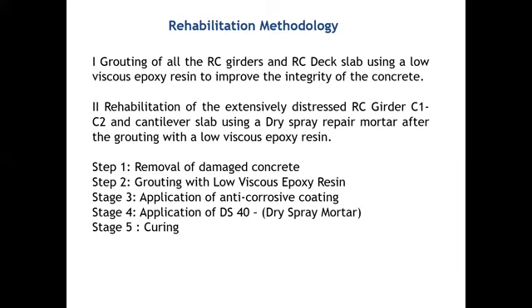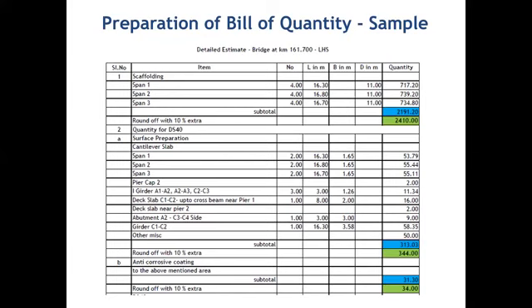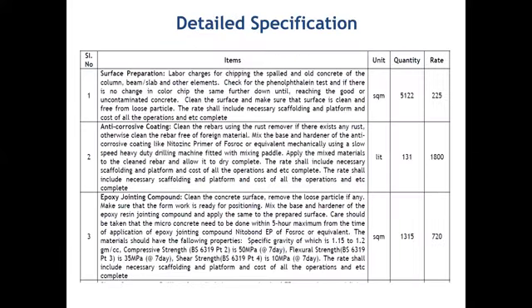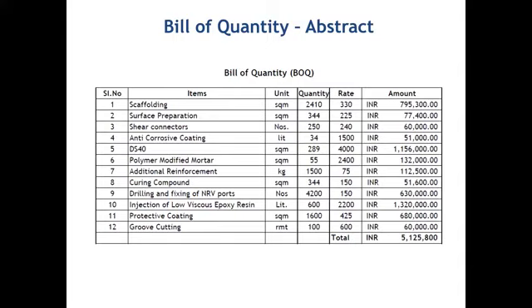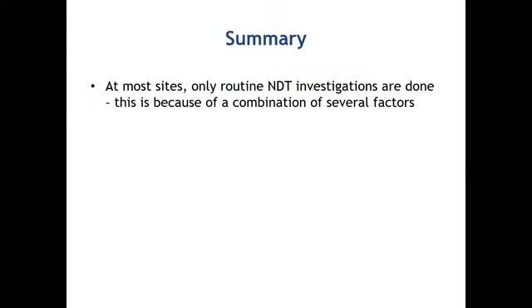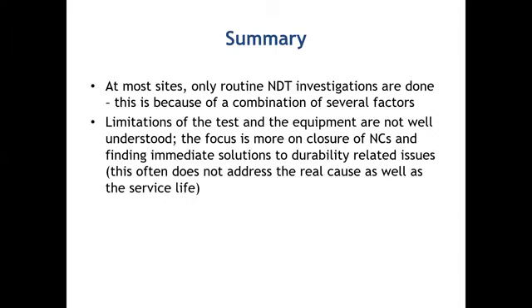For a minor one, you can go with either dry spray mortar or polymer modified mortar, then finish off your bill of quantity. On most sites, only the routine NDT is done, because a combination of several factors has to be taken into account. The limitations of the test and equipment also matter.